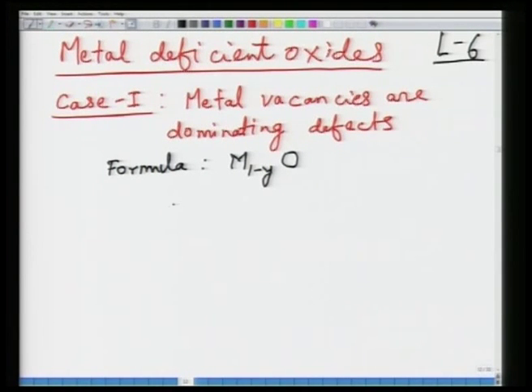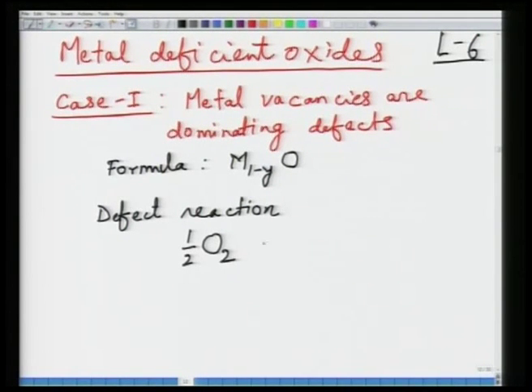And the possible defect reaction that would occur is, since it is a case of metal deficiency, you have oxygen coming in, oxygen goes to oxygen site. We are taking the case of MO type, which means now you have to maintain the site balance. So you create one oxygen site where the oxygen goes, complementing that you have to have a metal site, but since this is a metal deficient oxide, you will have vacancy of metal. Now, this vacancy of metal, since it is a MO form, would be doubly negatively charged. Now, this can be complemented, for example, by formation of two holes. So, this is your electronic compensation. Basically you have creation of holes, and as a result, just like in the previous case, this forms a p-type conductor.